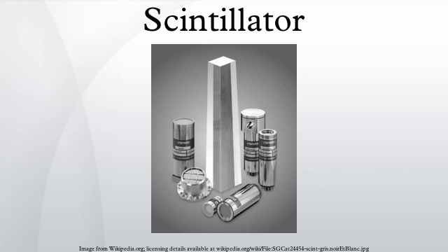PbWO4, or lead tungstate. Due to its high Z, PbWO4 is suitable for applications where a high stopping power is required. Lu2O3, or lutetium oxide. LSO, or lutetium oxyorthosilicate, is used in positron emission tomography because it exhibits properties similar to bismuth germanate, but with a higher light yield. Its only disadvantage is the intrinsic background from the beta decay of natural 176Lu.